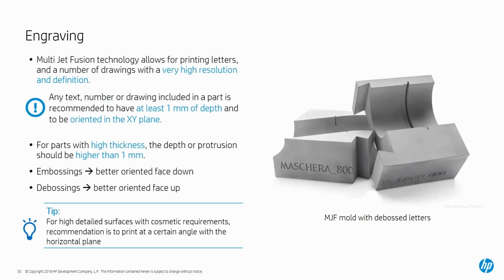If we're engraving or putting text onto a part, embossing or debossing, and the text is extremely important, we're probably going to change the orientation it faces in the build, right? If text, or any part on the bottom plane of the XY, is facing down in the Z, it's going to have a more rounded-over or smoother finish. If it's facing up in the direction of Z, it's going to have crisper detail. The reason is the way we apply the agents and fuse layer by layer. The facing-up surface is the last thing that sees a detailing agent, and it's not going to be fused again. If it's on the very bottom of the part facing down in the Z, it's going to be fused over multiple times throughout the build, and it's going to have a smoother surface. So it depends on what you're trying to achieve with the part.